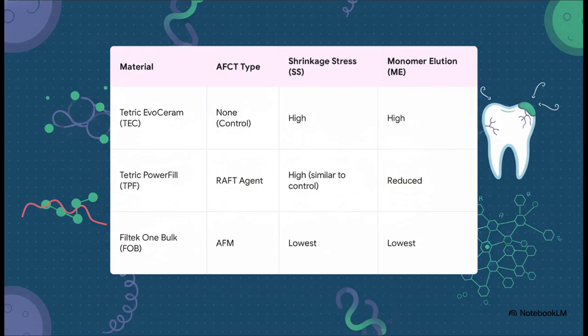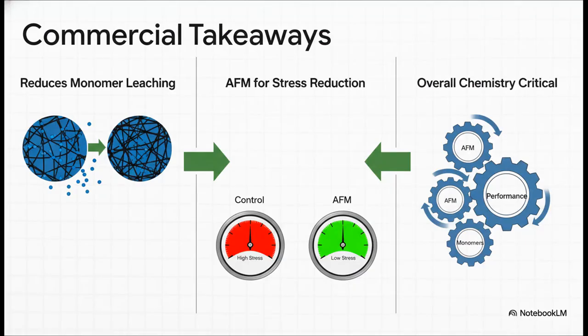The Filtek One Bulk, the one with the AFM, had the lowest shrinkage stress and the lowest amount of unreacted monomer leaching out, which is a great sign of a really well-cured material. Now, what's interesting is that the RAFT-based material had stress levels pretty similar to the control, even though it did help reduce that monomer leaching. So what are the big takeaways from the real-world products? First, adding these kinds of adaptable links to the network makes for a better, more completely cured material, which is great for biocompatibility. Second, at least in this head-to-head comparison, the allyl sulfide-based AFM was way more effective at actually reducing stress than the RAFT agent was.